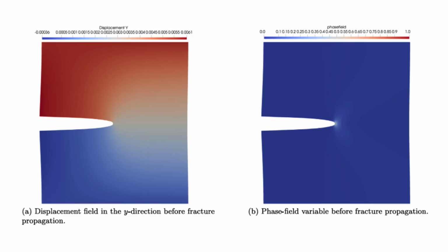Oh, yes. Other studies focusing specifically on solver efficiency for PFM have shown that switching from AM-type schemes to something like LBFGS can cut the CPU time down dramatically. We're talking factors of 3 to 7 times faster. A potential sevenfold speedup just by changing the core solver. That's huge. That could turn days of computation into hours. It's transformative, but there's more.